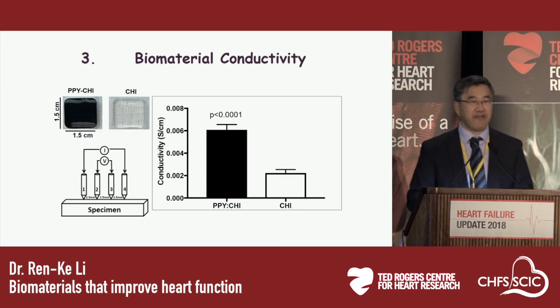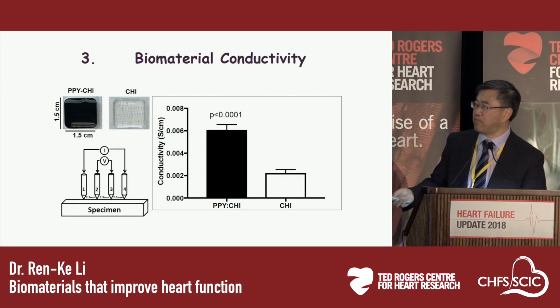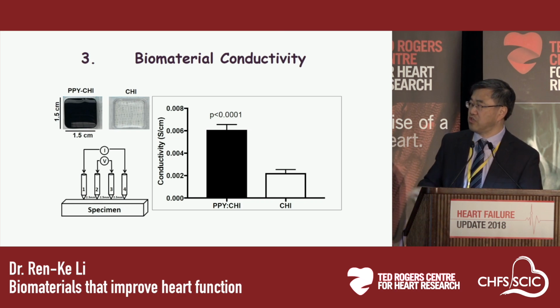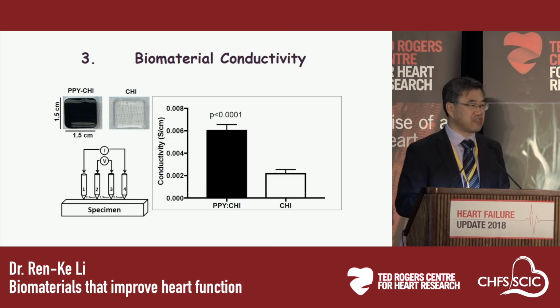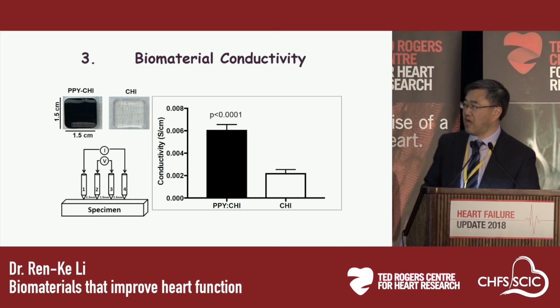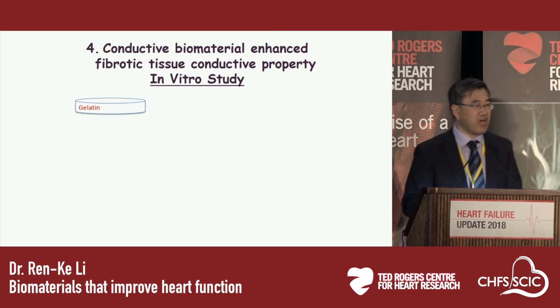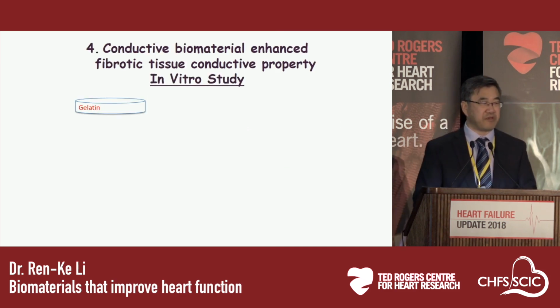So we have this biomaterial, and we want to know how conductive it is. We use this 4-probe machine to measure the conductivity of the conductive biomaterial. We find it's 3 times higher compared with a control material. So now we have the conductive biomaterial.